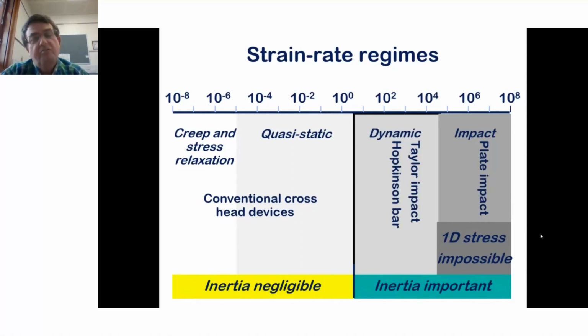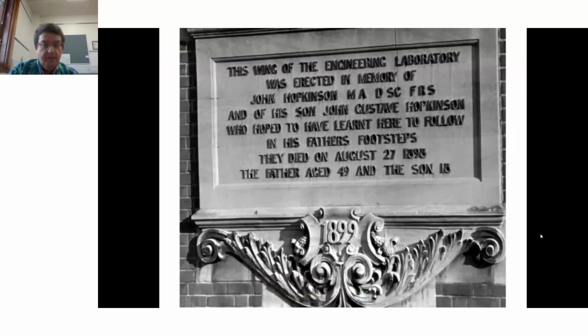And what we have here is a rough division between creep and stress relaxation processes, quasi-static processes, and dynamic processes, which tend to be 10 to the 1 and above: Hopkinson bar, Taylor impact, which I'll mention in a little more detail, ultimately going up to regions where the sample basically doesn't have time to respond in a homogeneous fashion. The system becomes very much wave dominated, and that's investigated in the shock regime. And you can see at the bottom, inertia is negligible at low rates, increasingly important as you go to those higher rates.